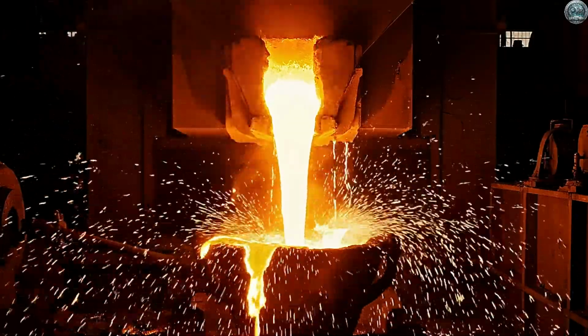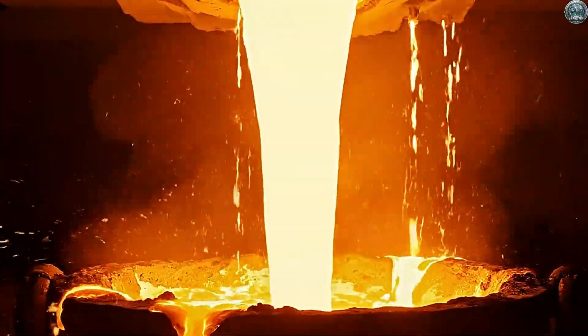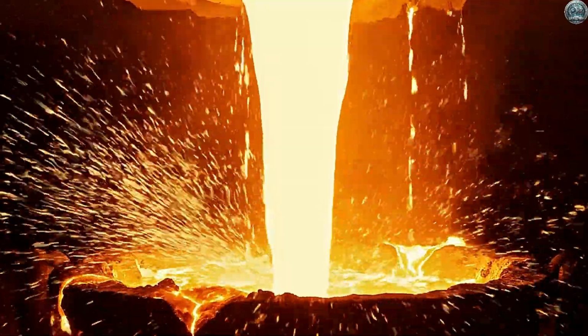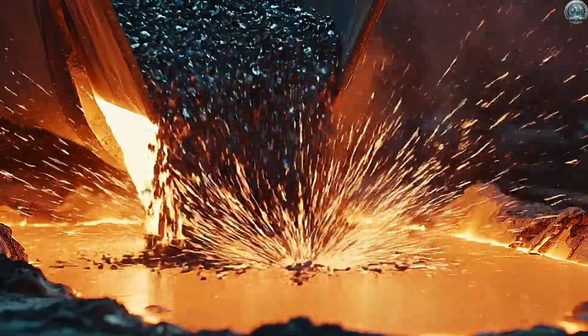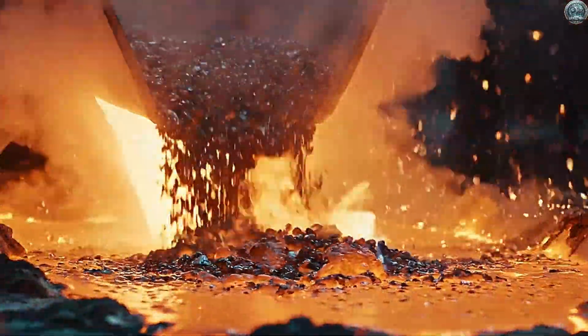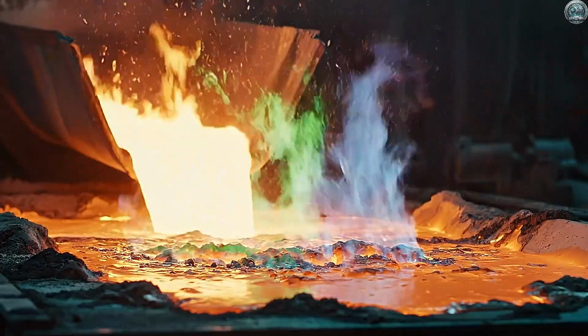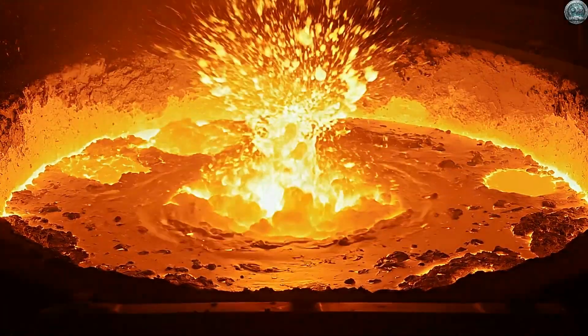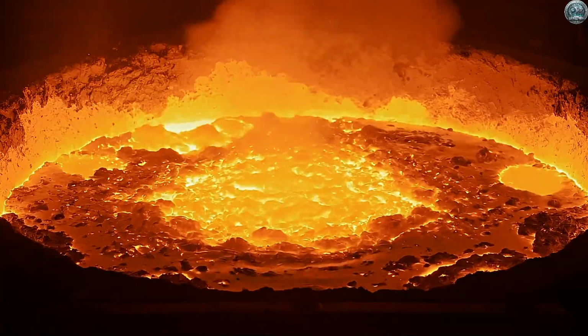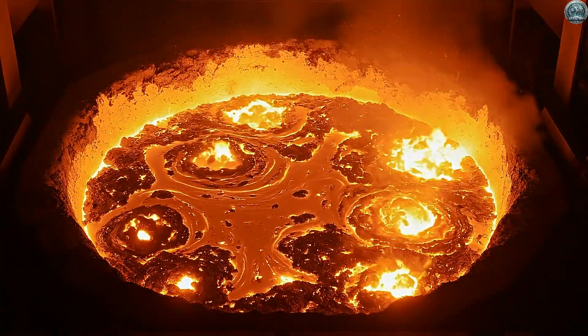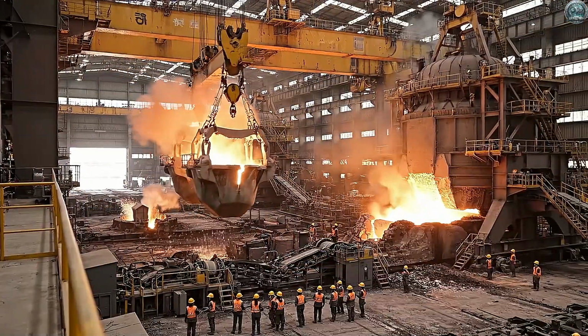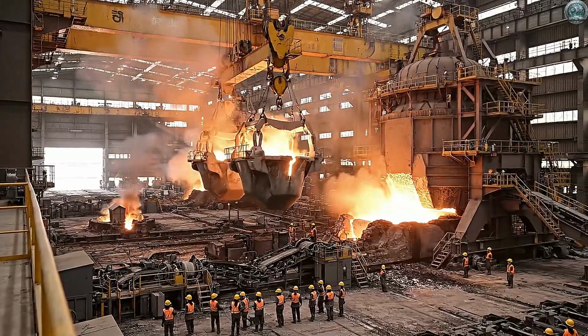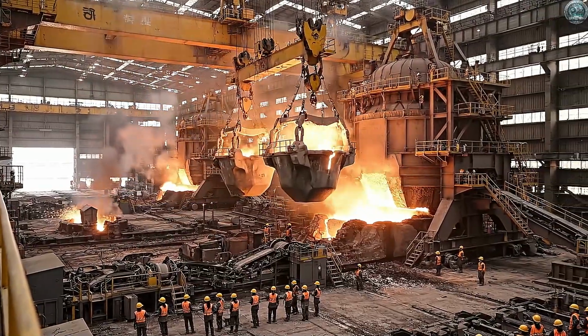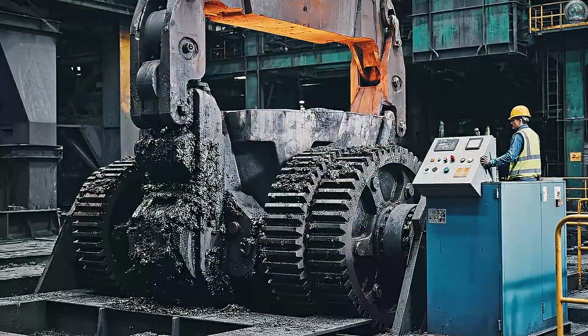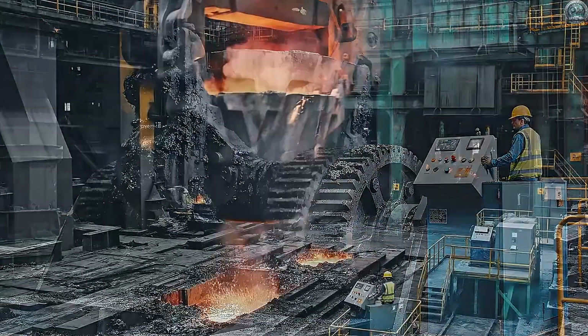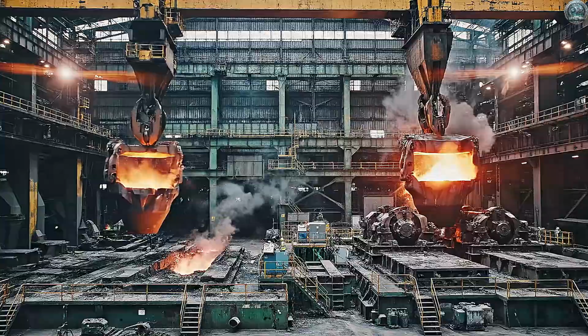Liquid steel cascades into the waiting ladle, a stream of pure light pouring through the darkness. Critical alloys are added to the stream, adjusting the steel's properties to meet precise engineering specifications. Gas bubbles gently stir the molten mix, ensuring uniformity and temperature balance throughout the ladle. The ladle touches down on the turret, rotating into position with the grace of a mechanical giant.